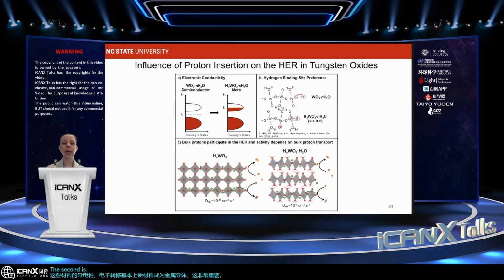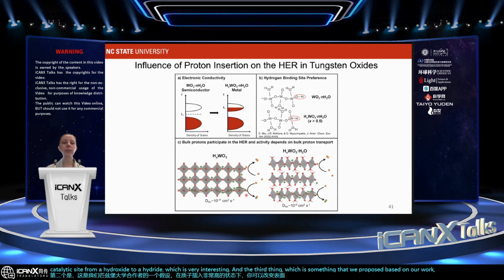The second is, and this is a hypothesis from our collaborators at University of Pittsburgh, that at very high states of proton insertion, you can be transforming the surface catalytic site from a hydroxide to a hydride, which is very interesting. And the third thing, which is something that we propose based on our work, is that there's actually the possibility of the involvement in the hydrogen evolution reaction in not only those protons that are available at the surface, but the protons that are inserted into the bulk of the material.